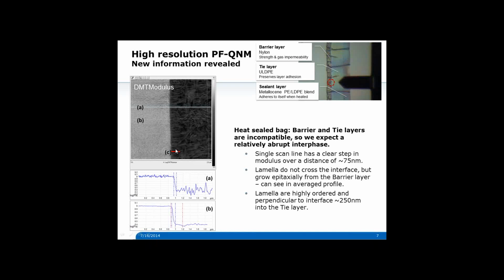You can see that there are lamella that are not crossing the profile from one component to another, but are growing epitaxially from the barrier layer. Those go for around 250 nanometers into the tie layer. They're highly ordered in this area, and then they become disordered in this part. The reason for the modulus changing here is likely because of these things being so ordered. And the length scale of the lamella is thought to be determined by the linear segment length of the polymer during processing.